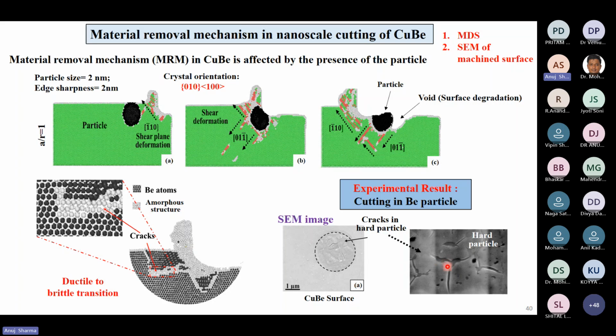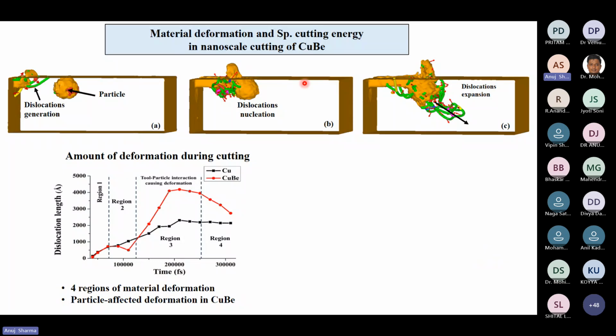These cracks were observed in the hard particles. Similarly, these dislocations were also analyzed. It was seen that initially this copper has a certain dislocation, and when it comes closer to the hard particle, they become nucleated because the dislocation flow is hindered by the hard particle.